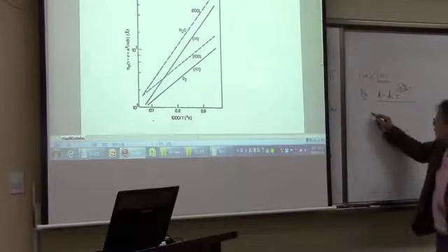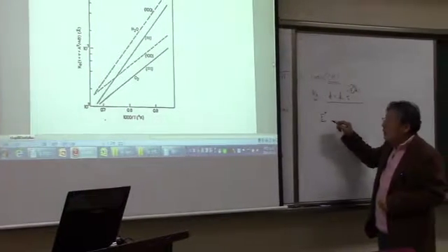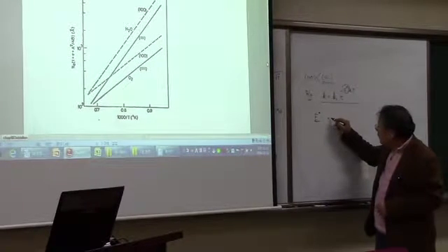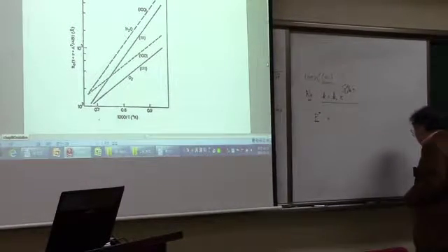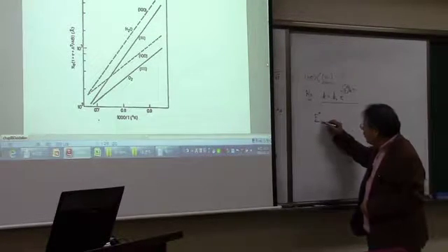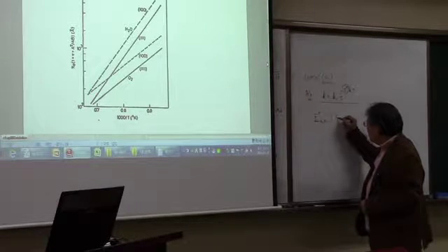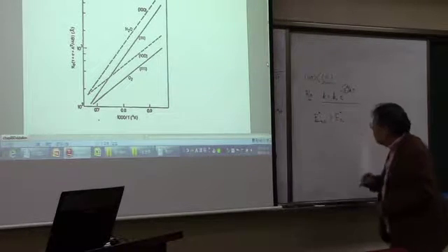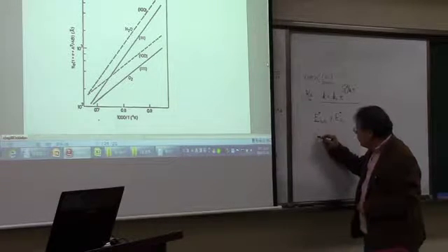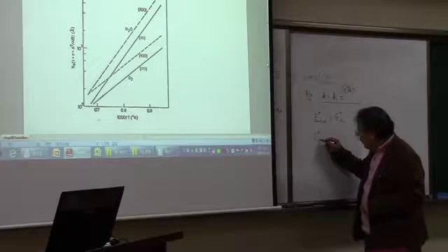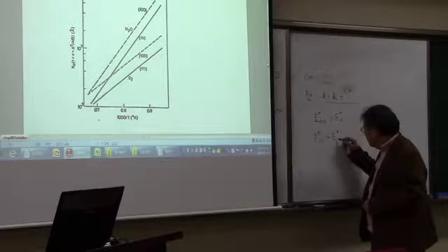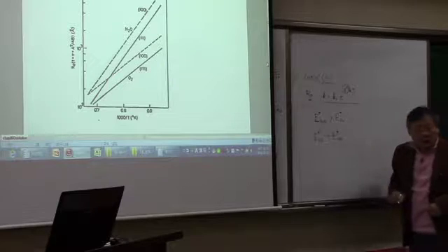This E star is different depending on the environment, okay? So the activation energy for the H2O is greater than the activation energy of O2, okay? But the activation energy in 111 is the same as the activation energy in 100.